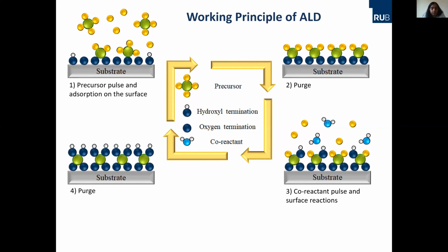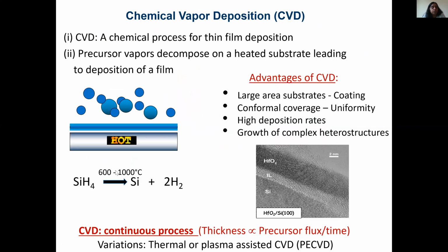And the difference when compared to CVD is that in CVD, you have a substrate surface. Imagine you want to grow silicon, which is one of the workhorse materials of the semiconductor industry. In this case, you have silane as a precursor, which will decompose at high temperatures, maybe 600 degrees, and form silicon, and hydrogen is released as a byproduct. So you have a thin film of silicon. Here it decomposes, so basically CVD is a continuous process. The thickness of the layers is controlled by the precursor flux and time.